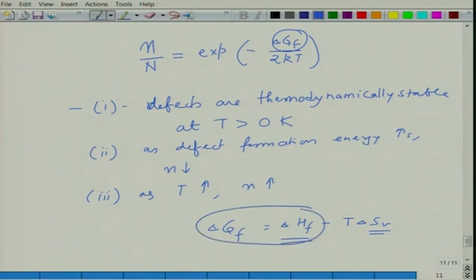And third is, as temperature increases, n increases, and this happens in an exponential manner. You can further simplify this, you can write this delta Gf as delta Hf minus T delta Sv, where delta Hf is the enthalpy of formation of defects and delta Sv is the vibrational entropy change, but it is approximated as delta Gf equal to delta Hf, because the vibrational entropy change is very small. So you approximate this as n by N equal to exponential of minus delta Hf divided by kT, where Hf is the enthalpy of formation of defects.